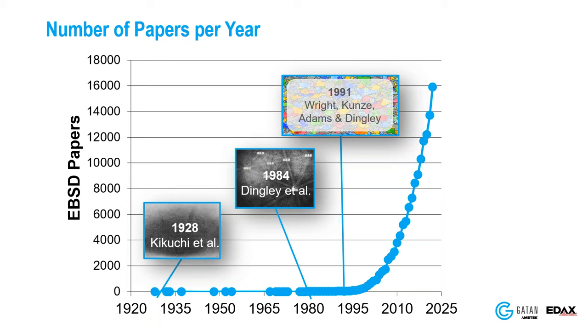Question: How do you prepare an organometallic crystal sample for EBSD analysis? Sample preparation is an important point. EBSD is very much a surface technique, so preparation of the surface is important. If you have a deformed or fractured surface you can get some patterns, but it can be difficult to map. If you impart too much deformation during mechanical polishing, you'll capture a deformed microstructure even on a recrystallized material. You have to be careful to achieve a finish that has no deformation from the polishing technique. We do a lot of mechanical polishing, but on really difficult samples we might finish with a broad beam ion polish or a chemical polish.